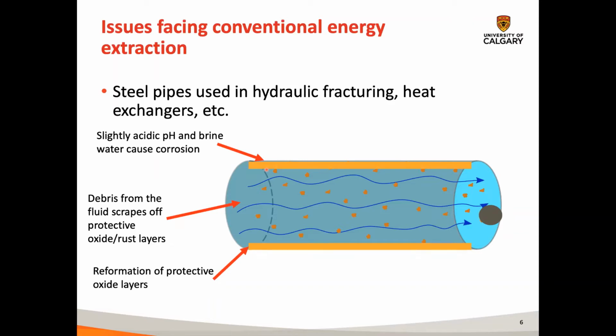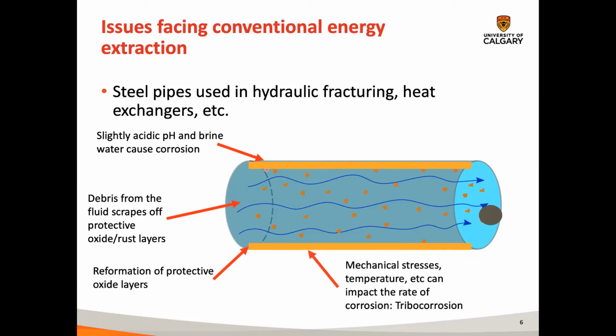And this process is happening over and over and over again. And so you're basically accelerating the corrosion by rubbing off the protective rust and then reforming it. So it's just corroding the metal very quickly. And so the other thing that can happen is with mechanical stress, so shear stresses, temperature, you can change the rate of corrosion so that it's much faster than you would see maybe if you were just dipping it in a piece of cold water. And so the impact of mechanical stresses in particular is of very interest in the field of tribocorrosion.